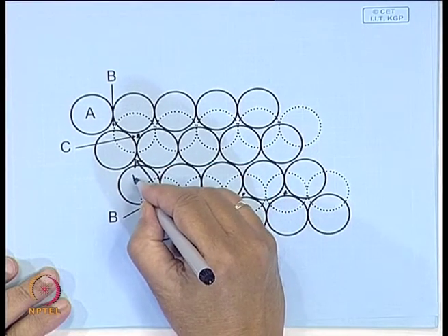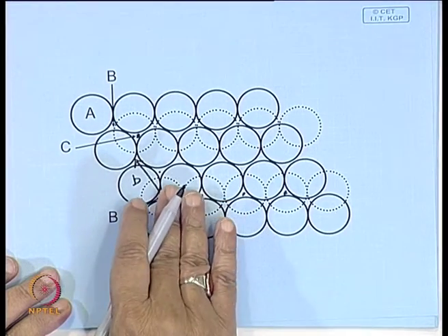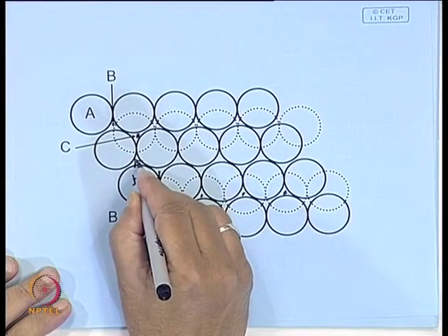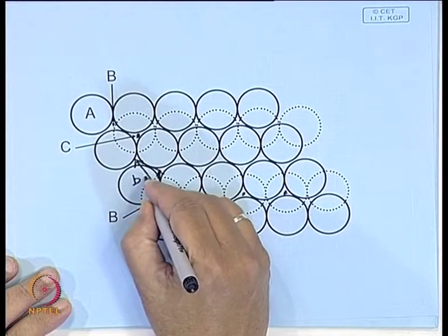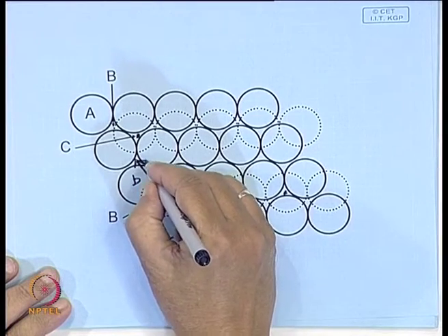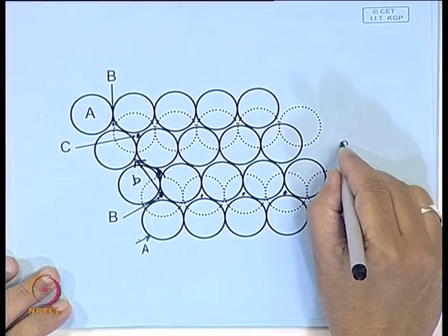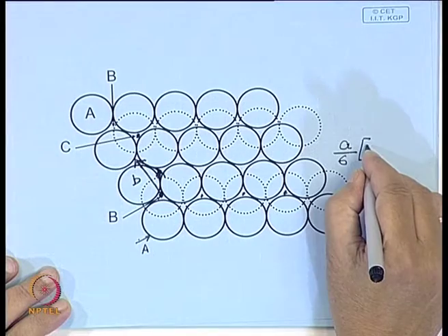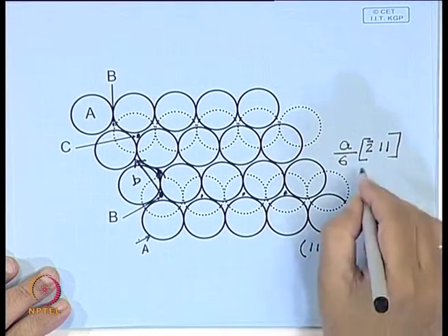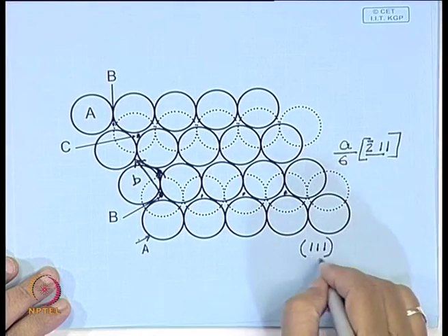So, basically this is the perfect dislocation Burgers vector. What is happening is as if this atom has to go over the sphere, part of the sphere, whereas instead of going like that, if it moves through the valley, it is more energetically favorable. So, this perfect dislocation is split up into two partials, one like this, another from here to here like this. These are called partial dislocations, and their Burgers vector is of the type a/6<211> kind. If this plane is 111, then the Burgers vector will be lying on the plane.